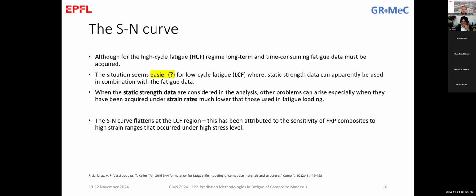What can improve this situation, these difficulties that we have there, is to include the static strength data in the analysis. We've seen methods that help to use static strength data, but there we should be very careful to take into account the differences that we can see in the lifetime of the material because of the different strain rates. We've seen yesterday that strain rates in fatigue are usually much faster than strain rates in static testing. So if we don't have data that correspond to the same strain rate, especially for composites that are viscoelastic, then we see that the fitting is quite poor there.